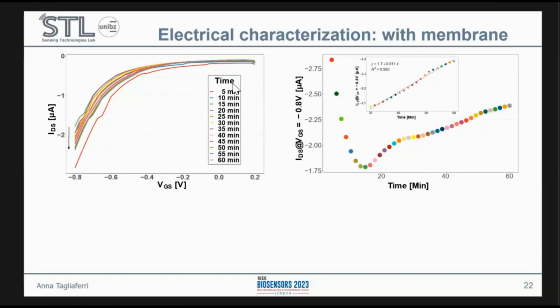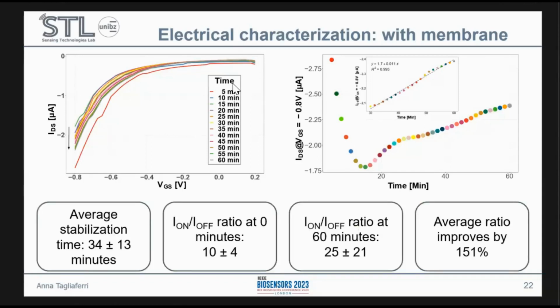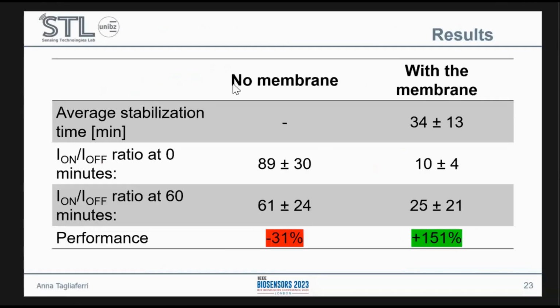We then performed the same parameter extraction as before, and we found that it takes on average 34 minutes for our devices to reach a linear current trend over time. And the performance also improves over time. We start from an on-off ratio of around 10, and after 1 hour, it more than doubles to a value of 25. So the overall improvement in the performance is close to 151%.